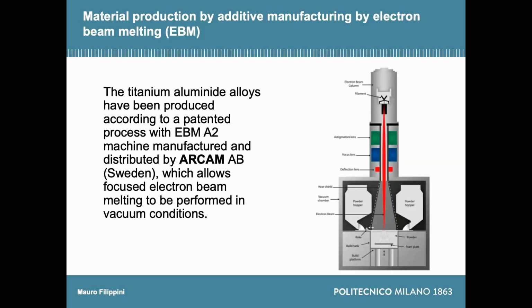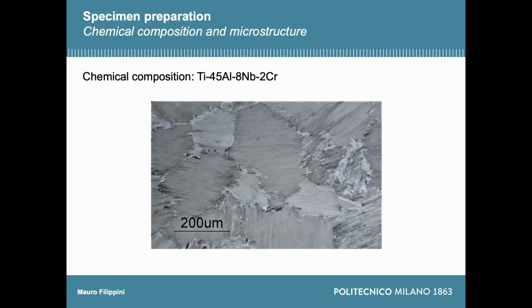The material is produced by EBM. It's not selective laser melting, it's EBM, and you need to produce the material in high vacuum in order to avoid oxidation and oxygen pickup by the material during production. The final microstructure is this one that I am showing. The final microstructure is obtained after EBM plus hipping plus heat treatment. So if you ask me about pores, there are no pores technically. This type of microstructure is not the target one. It's a mistake, I would say, in terms of microstructure. You would rather prefer to have a smaller colony size of your lamellar grains.